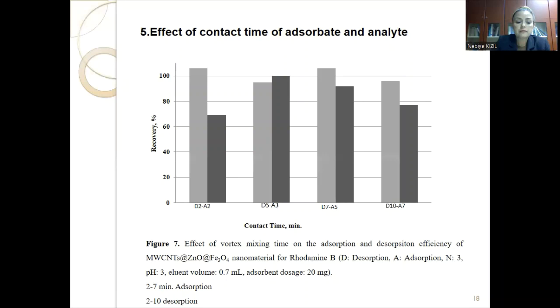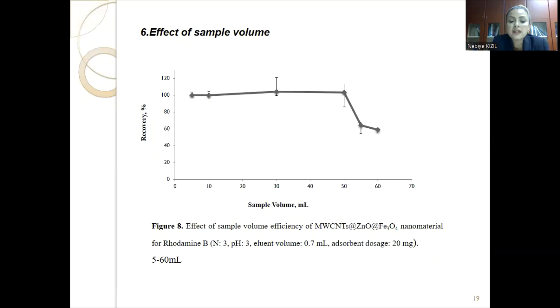Sample volume. To find the highest sample volume, model solutions were prepared in the range of 5 to 60 milliliter. Quantitative recovery values were obtained until 50 milliliters. Since the final volume used is 0.7 milliliter, the concentration factor was calculated as 71.4. We obtained the pre-concentration factor.